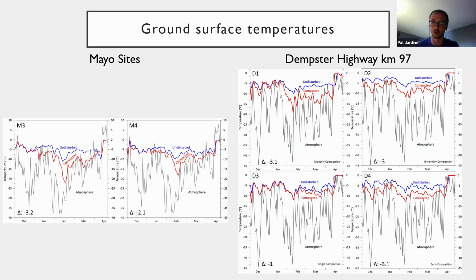Early in the winter, when air temperatures were relatively warm and often swung near 0 degrees, temperatures of the compacted and undisturbed plots were mostly coupled together. In the second half of January, a sustained cold spurt hit, and mean daily temperatures quickly dropped to below -35 in Mayo and below -40 at the Dempster. This caused temperatures of the compacted and undisturbed plots to diverge, with the greatest differences in temperature between the plots being recorded in February, and that was 9.6 degrees at D1 for the Dempster plots and 12.1 degrees at M3 for the Mayo plots. After this cold spurt, the difference in temperatures was reduced and stayed mostly steady at about 4 or 5 degrees until the thawing season.